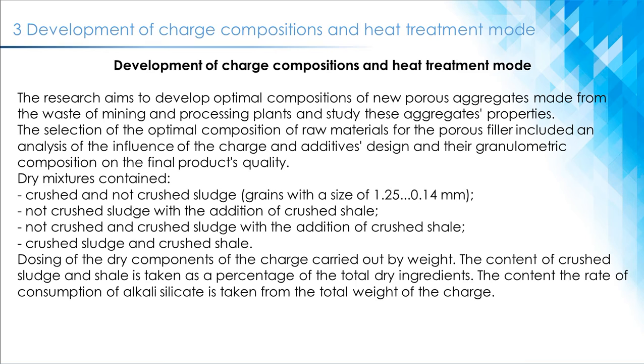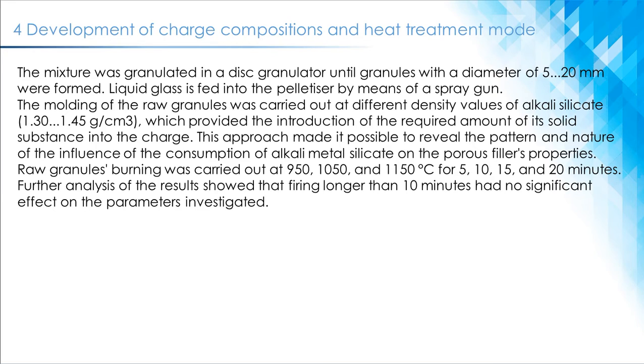Dosing of the dry components of the charge was carried out by weight. The content of crushed sludge and shale is taken as a percentage of the total dry ingredients. The rate of consumption of alkali silicate is taken from the total weight of the charge. The mixture was granulated in a disc granulator until granules with a diameter of 5-20 mm were formed. Liquid glass is fed into the pelletizer by means of a spray gun.